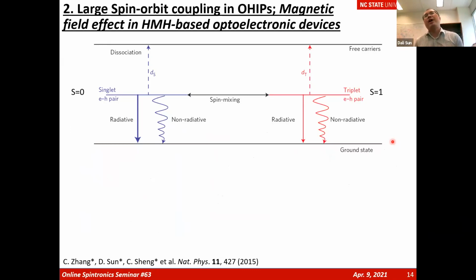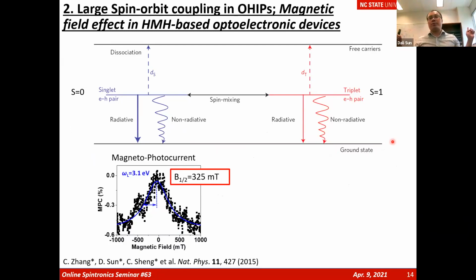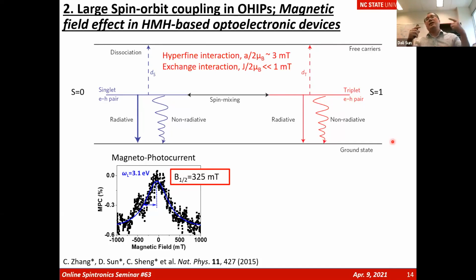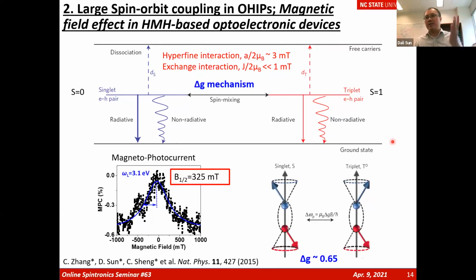So we studied the spin-orbit coupling effect in hybrid perovskite materials using the magnetic field effect. We observed the photocurrent changes proportionally as a function of magnetic field, forming a Lorentzian shape. And this indicates a singlet electron-hole pair formation and transition to the triplet electron-hole pair due to intersystem crossing, because a singlet has two spins of the opposite, the triplet has two spins to be correlated. This intersystem crossing between two electron-hole pairs can be only caused by the delta g mechanism in this specific case. Because the electron and hole have different g values, when you apply a magnetic field, they have different spin precession speed. So then you're able to convert the singlet configuration to the triplet configuration that will be responsible for the magnetic field effect we observe in the photocurrent, electroluminescence, and also the photoluminescence.